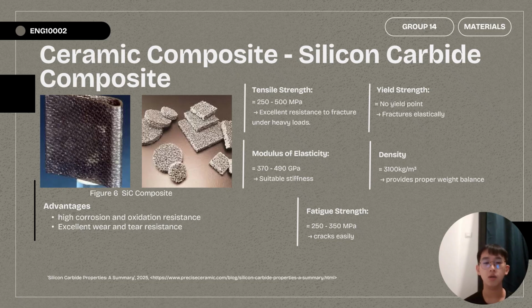The density of silicon carbide composites is around 3.1 grams per cubic centimeter, and the fatigue strength of silicon carbide composites is around 250 to 350 megapascals. It means the silicon carbide composites can crack easily. One of the important points is that silicon carbide, like other ceramics, does not exhibit a yield point. It fractures elastically when overloaded.